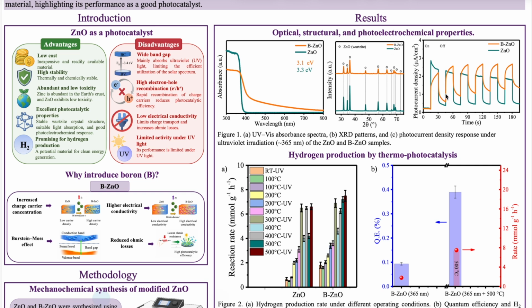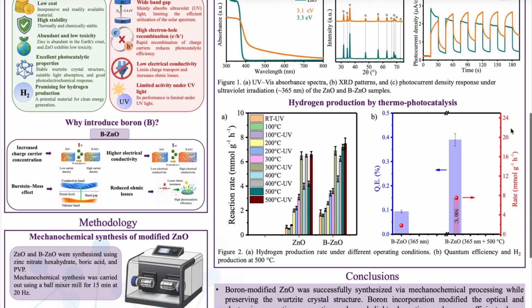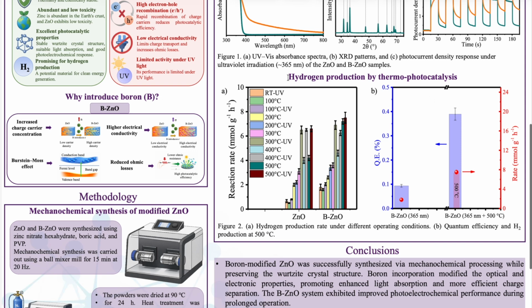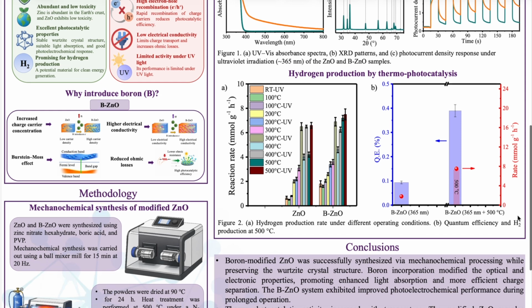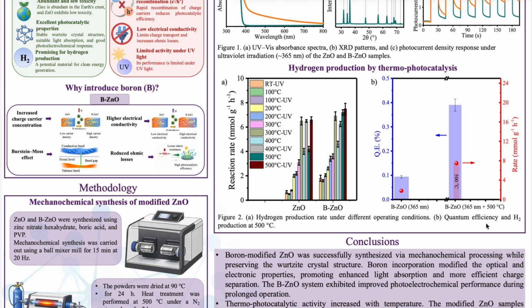Figure 1c shows the photocurrent density measured under ultraviolet irradiation. The boron-modified ZnO exhibits a significantly higher photocurrent response than pure ZnO, indicating more efficient charge separation and improved charge transport. Figure 2 summarizes the thermophotocatalytic hydrogen production experiments. As the operating temperature increases, the hydrogen production rate also increases. Furthermore, the boron-modified ZnO clearly outperforms pure ZnO in terms of both quantum efficiency and hydrogen production. These results confirm that boron incorporation enhances charge generation and separation, improves light absorption, and produces a synergistic effect that significantly increases hydrogen production.